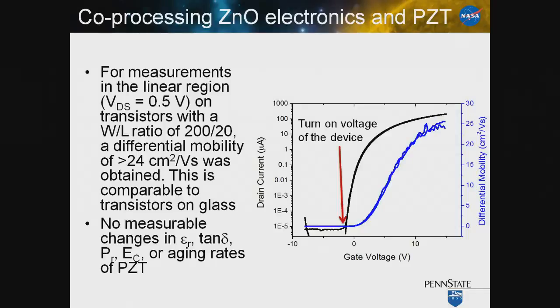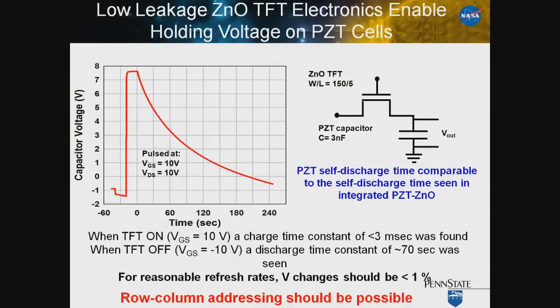There we go. And this shows the functional performance of the zinc oxide fabricated directly on the piezoelectric adjuster. And you can see that the two processes are essentially agnostic to each other. So the functional performance of the zinc oxide thin film transistor is completely identical to what we would have had preparing that on a standard glass substrate without the piezoelectric cell. And we've looked very hard for changes in the piezoelectric performance. We have been able to find absolutely no impact on the permittivity, the loss tangent, the remnant polarization, the aging rates, or the piezoelectric constants. So it is possible to marry these two technologies without degrading the constituents.